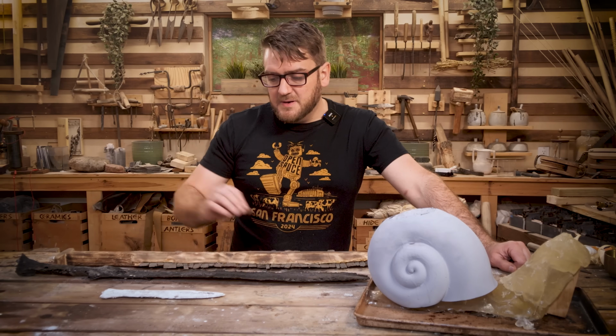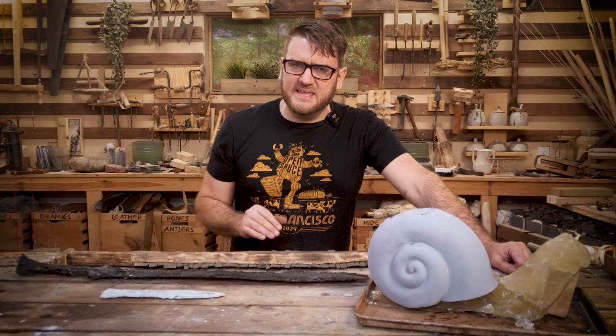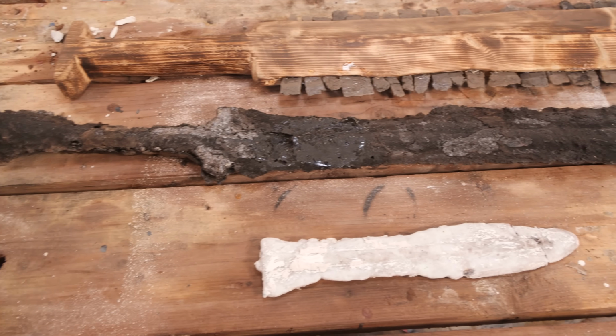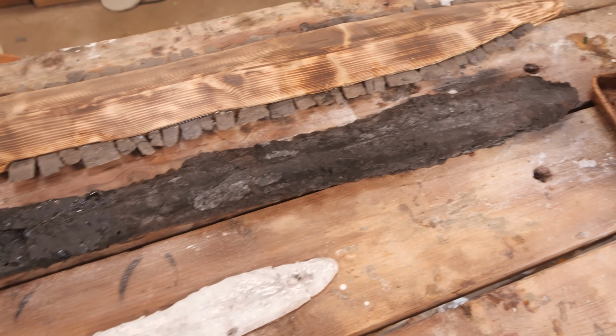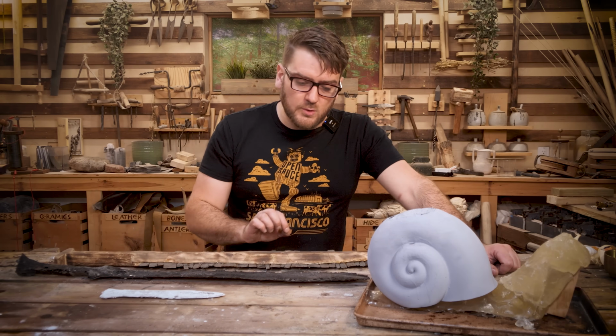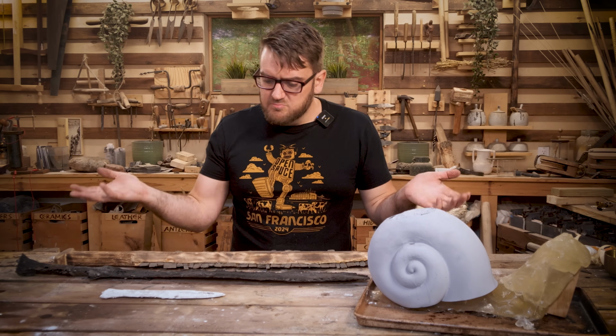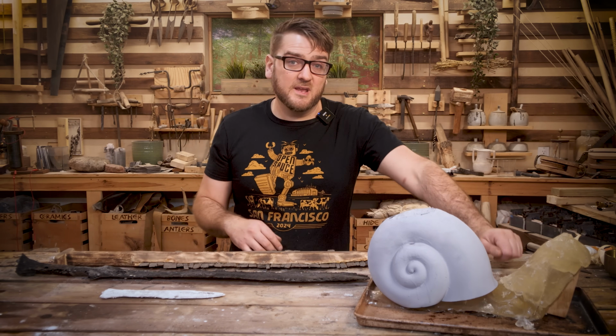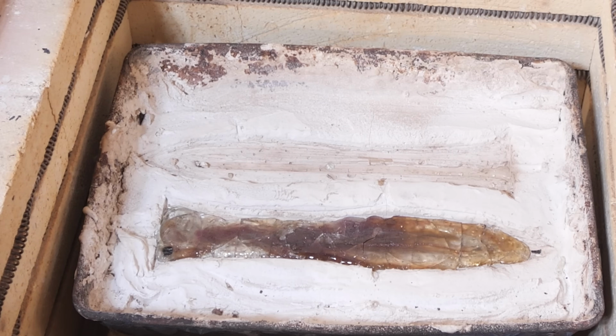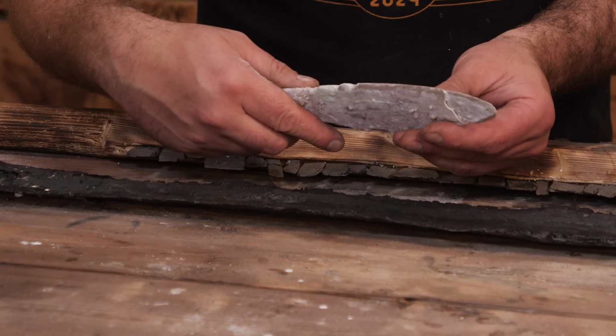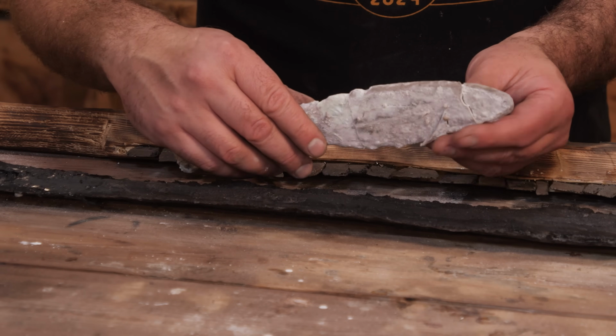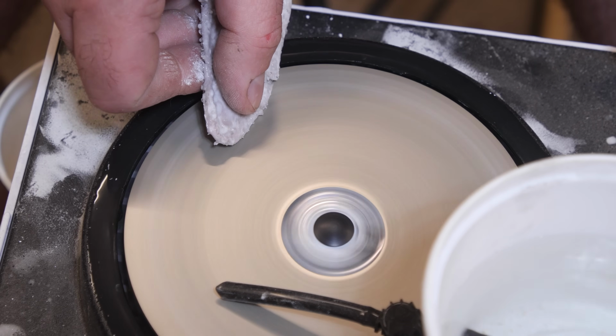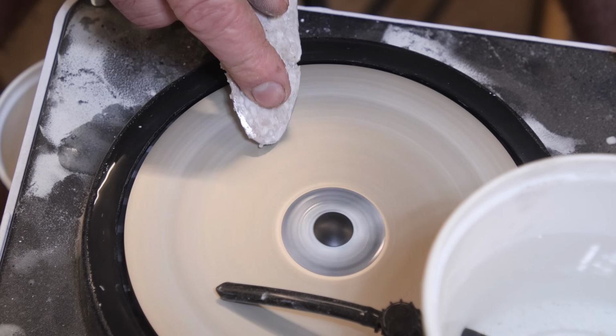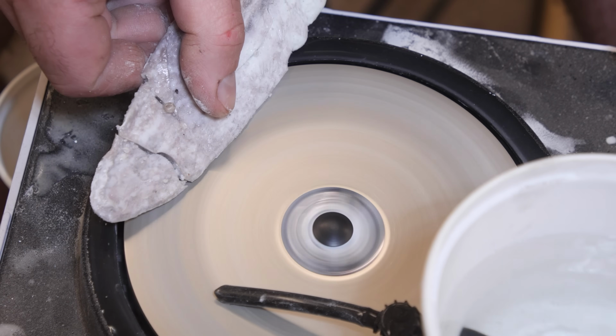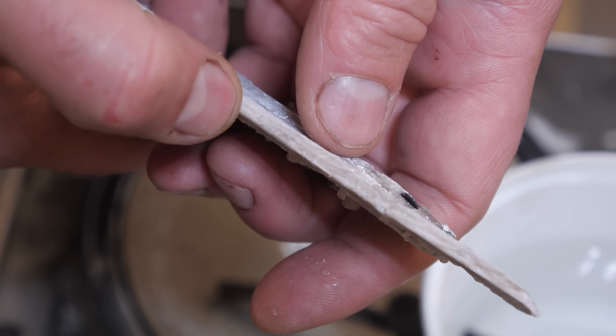So I think this has been kind of a fun experiment to mess around with and see what kind of results we can get with these different materials. I think this is probably kind of the best results we're gonna get with kind of our goal in mind, an actual solid sword. And we have 3 results of 3 potential possibilities of something working. So we have the borax. It ended up cracking before I fully annealed it, but I was able to get the temperature up hot enough to get it to kind of fuse together. Thin parts where it's fused, so there's a possibility it might break. And then I tried sharpening it and had decent success to get at least kind of a sharp edge, but it's not really hard material.